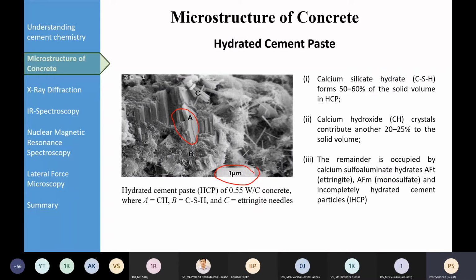Another is this B portion, a cloudy type of structure, and this is actually calcium silicate hydrate, and this forms 50 to 60% of solid volume in hydrated cement paste. And typically, as we have discussed, our priority is that there should be maximum calcium silicate hydrate, then calcium hydroxide, and the remainder is occupied by calcium sulfoaluminate hydrates, ettringite, etc. Like these needle type of structures. So they are basically ettringite type of structures, and they are the least preferred because they cause certain durability related problems in time.